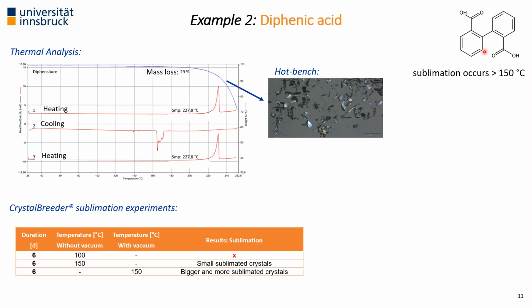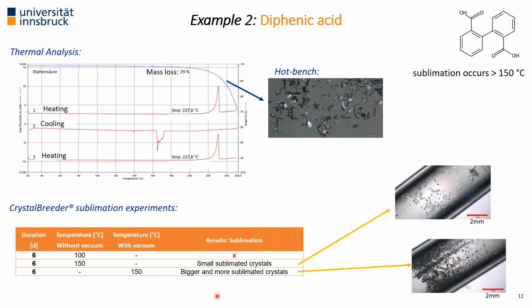So a few experiments have been undertaken with the crystal breeder. Here I'm showing the variability of temperature and whether reducing pressure helps or not. And here you can see the direct comparison of two experiments where sublimation was undertaken at 150 centigrade. We kept the sample for 6 days. Without reducing the pressure, we already see a few crystals, small but not too bad. By reducing the pressure, we can make sure that more crystals form, and some really nice ones like this one we can grow. So our advice is, if you have the possibility to reduce the pressure and you have a compound which shows sublimation at a higher temperature, then reduce the pressure. You have the potential ability to do the sublimation experiments at a lower temperature and grow more crystals.